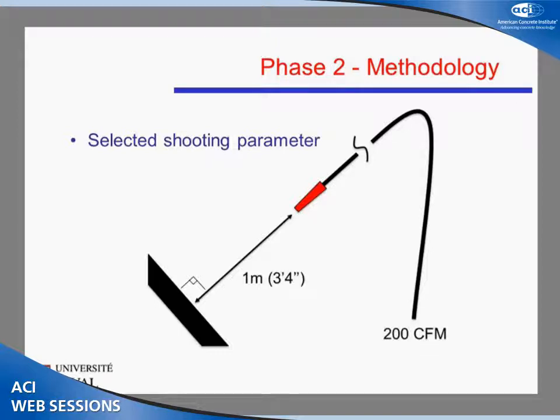Followed by 2 other things. The first is the distance. We're going to control the distance at about 1 meter, give or take an inch or so, so 3 feet, 4 inches. And we also want to control the airflow. Now this is 200 CFM. We chose 200 CFM as it's slightly over what we consider in-lab optimal conditions, just to get a little more compaction than you would need. This is the airflow that's measured in the nozzle, not the airflow you would see on the compressor, for example. What does this allow? It allows identical shooting energy. Essentially, it locks in a lot of variables that would otherwise provide a lot of variability in itself, in terms of energy, how it compacts.